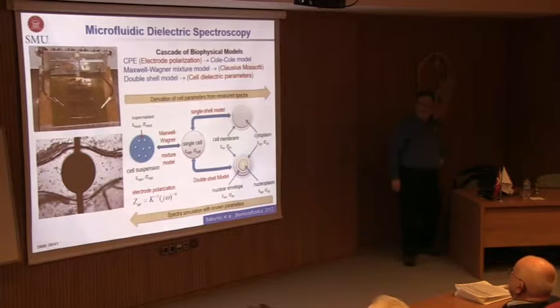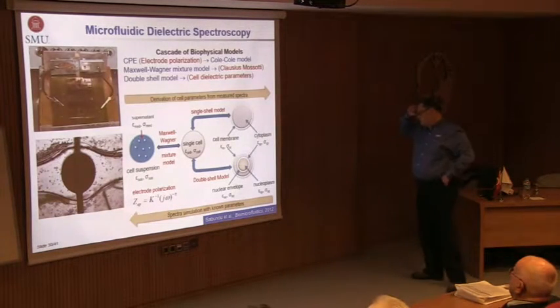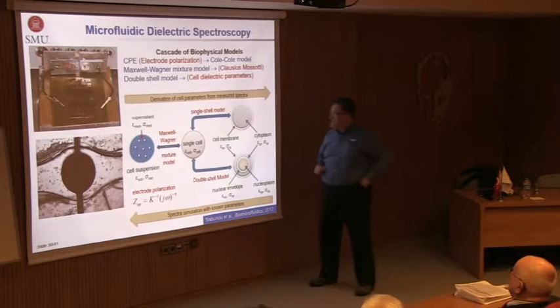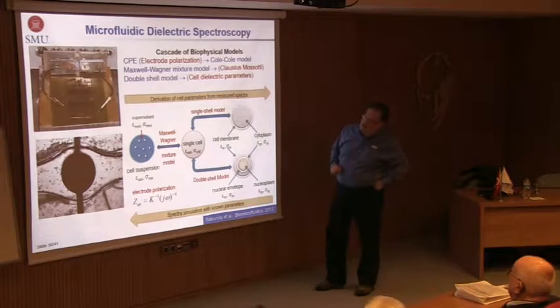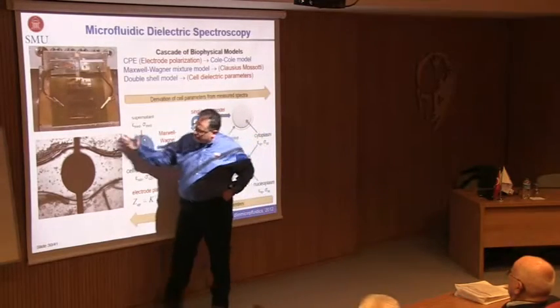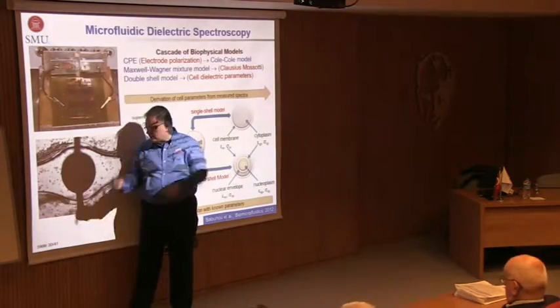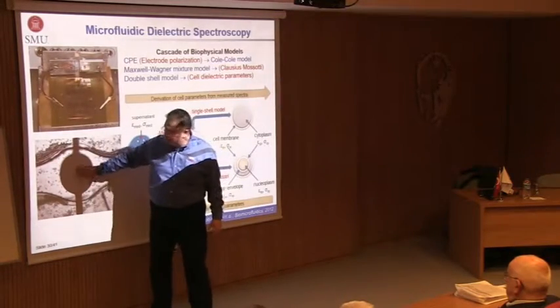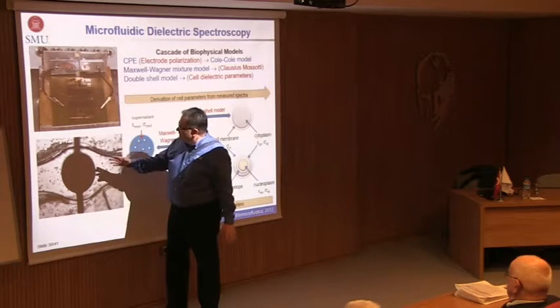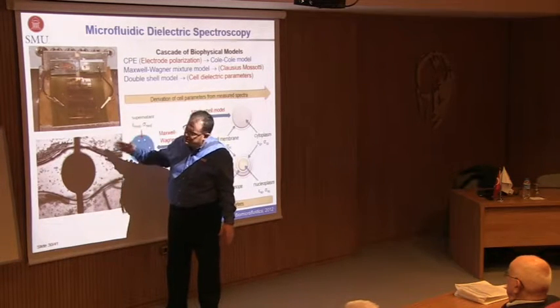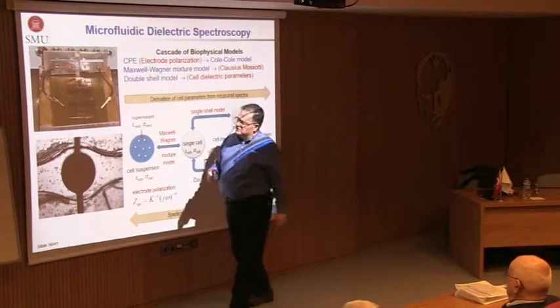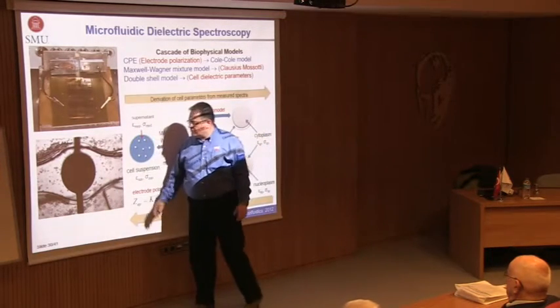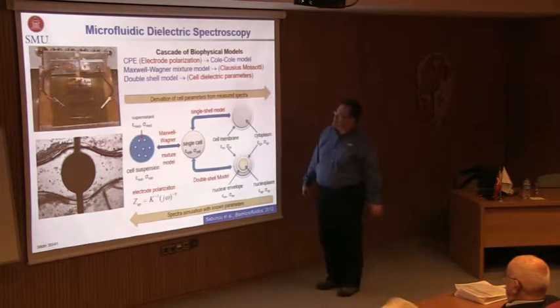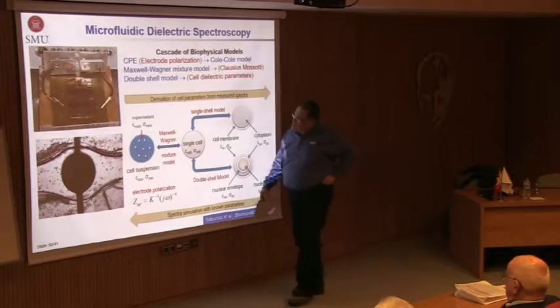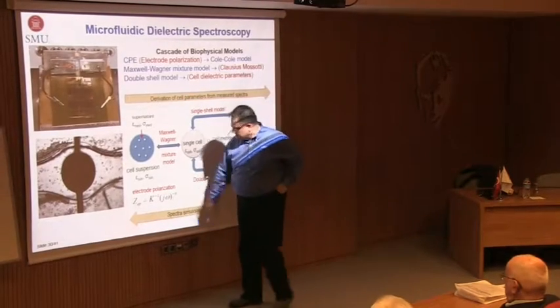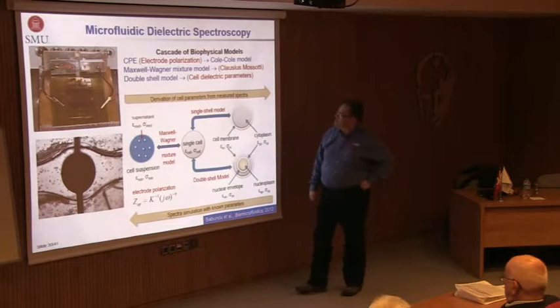First, let me talk about dielectric spectroscopy. This is a work with Ahmetcan Sabuncu, which was published in 2012 in Microfluidics. The idea is very simple. I can create a microchannel, and I can have two electrodes on the top and the bottom, and I basically put a bunch of cells in it, and then by using an impedance analyzer, I measure the electrical impedance in the frequency domain, from low frequencies up to maybe 100 megahertz. Then using this data, assuming a constant phase element model, which is described here, to take care of electrode polarization,